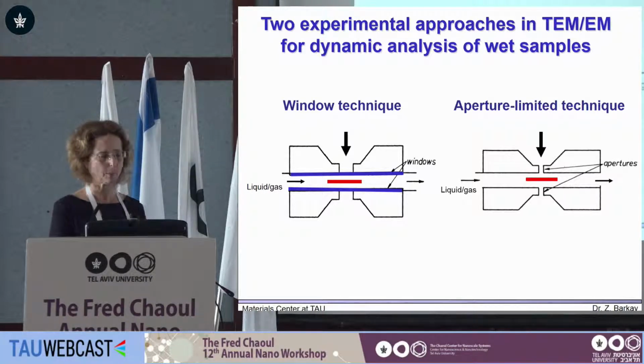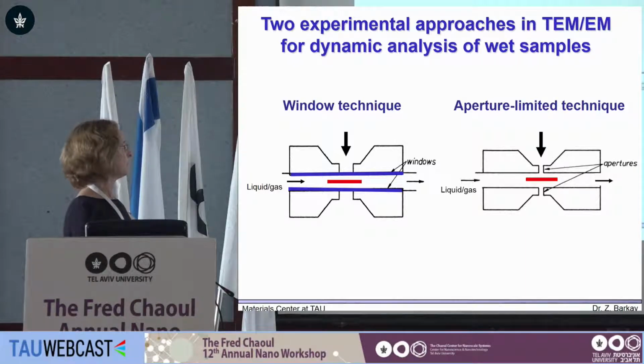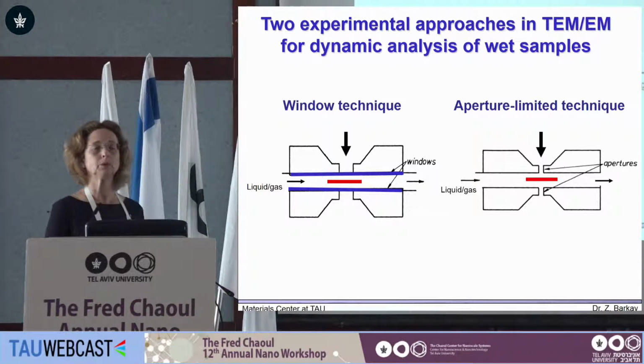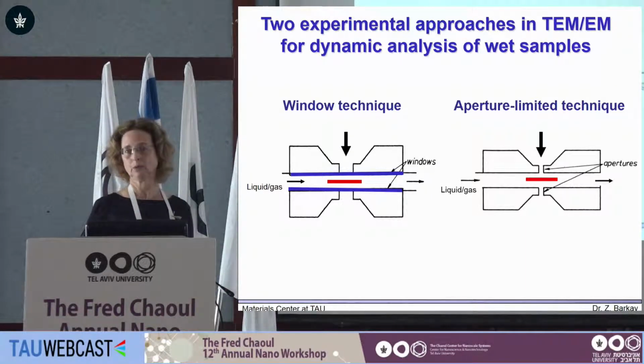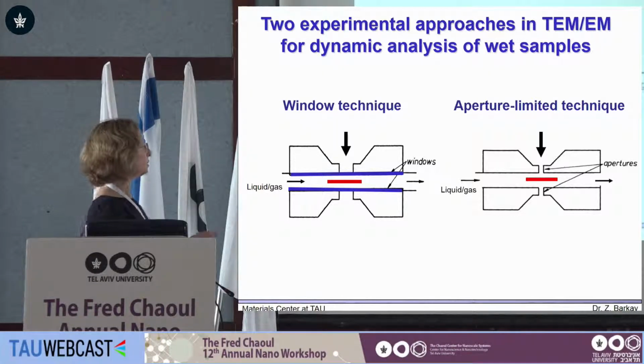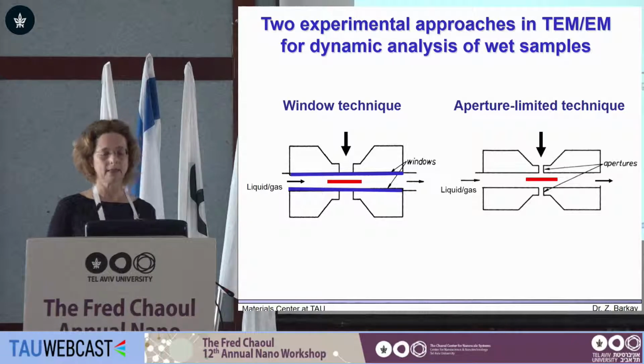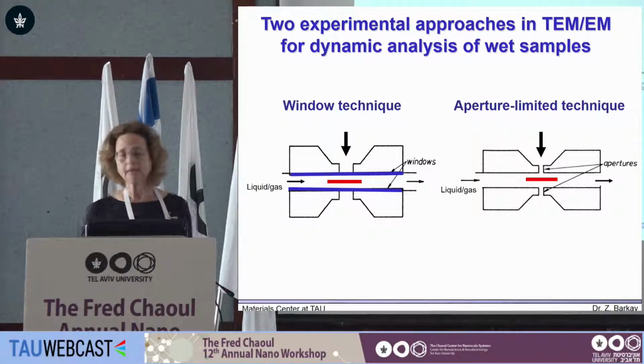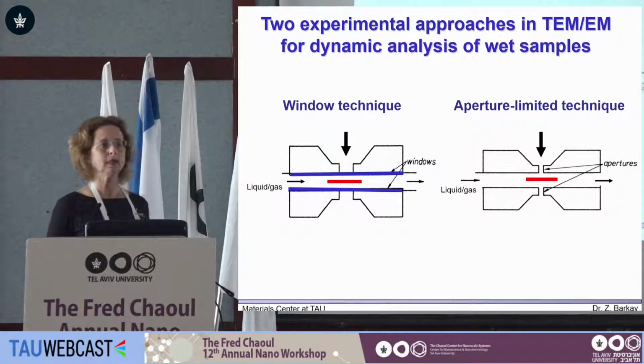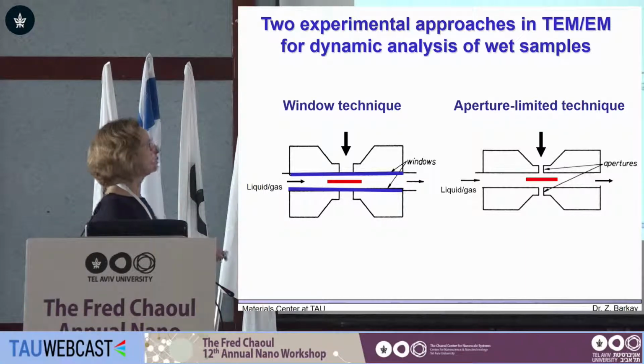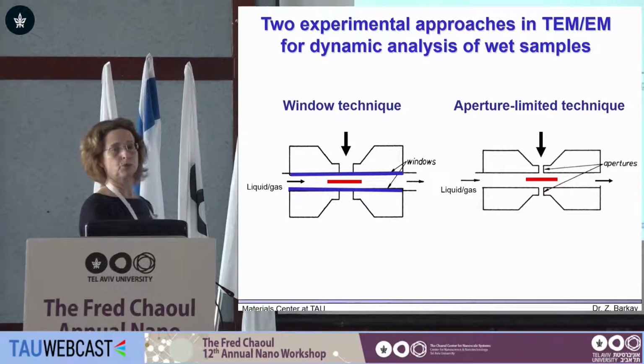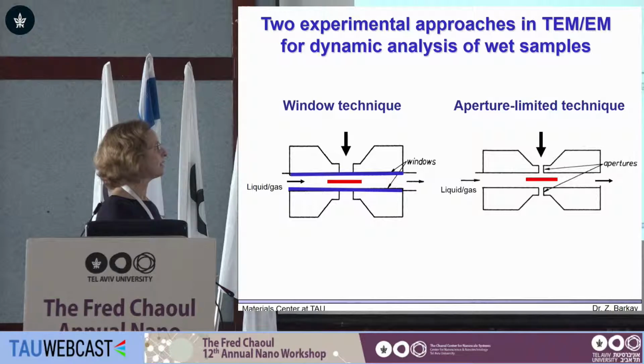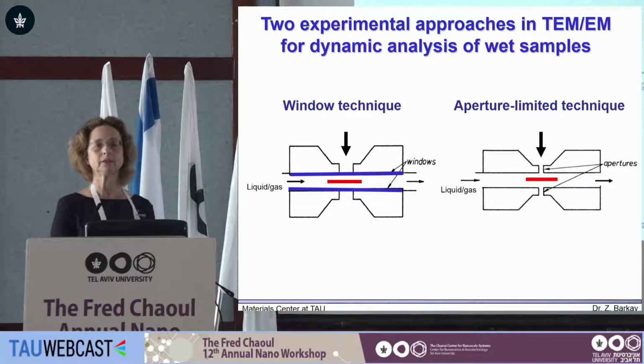We have the window technique, in which the liquid sample is inserted in between two e-beam transparent windows, so that the rest of the system is kept at high vacuum and only that area is kept at high pressure. And the second approach is the aperture limiting approach, in which the sample is sandwiched in between two apertures, above and below, with a pressure gradient maintained by differential pumping.